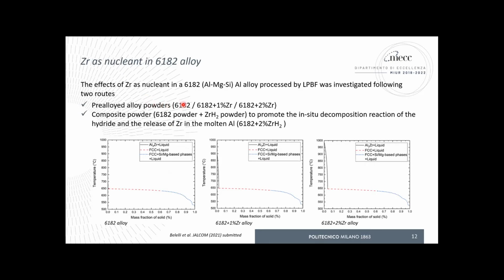Here, for instance, we have some example about using a 6182 aluminum magnesium silicon alloy that was modified by adding zirconium. By adding zirconium in the pre-alloyed powder, so melting a liquid alloy that already contains 1% or 2% zirconium and producing a powder out of it, or adding, as Maria Teresa was showing an example, zirconium dihydride powder to the powder of the 6182 alloy, and promote the in situ decomposition during the melting, so that we have zirconium available for the nucleation of the grain of the matrix, and hydrogen. There is an issue about porosity, but hydrogen in principle should escape from the melt.